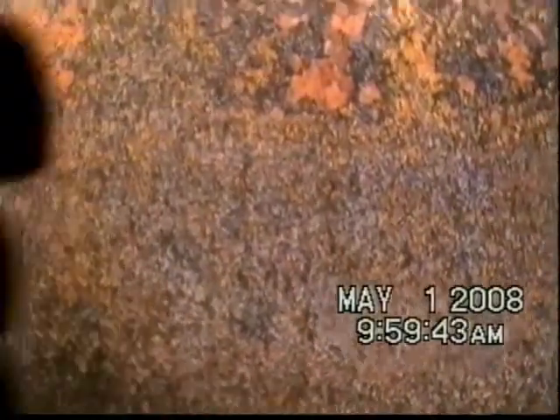This is an example of the condition of the super tank coating on ring number 1 near the waterline. Delaminating coating was observed in many locations on the shell near the waterline. Slight contact by the diver inspector would dislodge pieces of the super tank coating. Note the poor condition of the coating on the shell near the waterline. Extensive coating delamination is present on ring number 1 near the waterline.